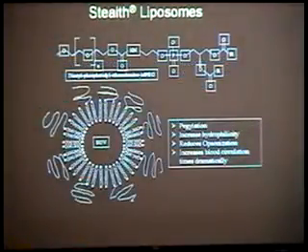And this is the basis of a company where I used to work, and we've put a couple products out on the market based on this using doxorubicin, a chemotherapeutic agent. And so the way these work is you've got a bilayer bounded vesicle now with a polyethylene glycol molecule hanging off the side. And this imparts sufficient hydrophilicity that you greatly increase the blood circulation time.